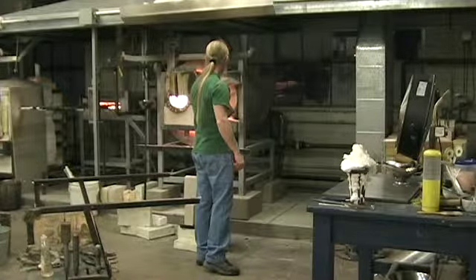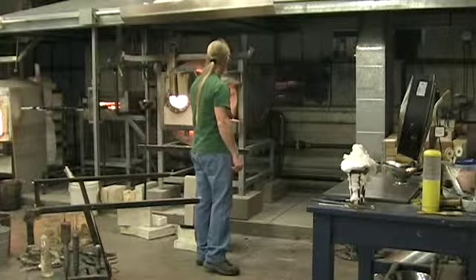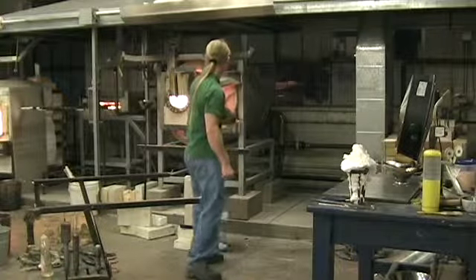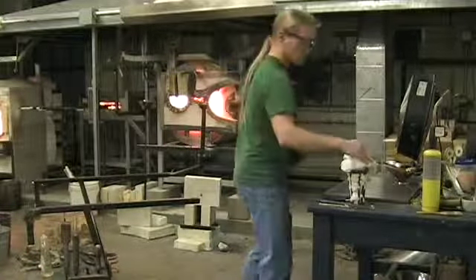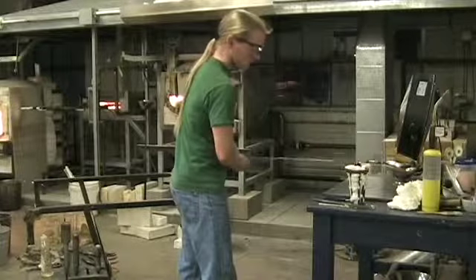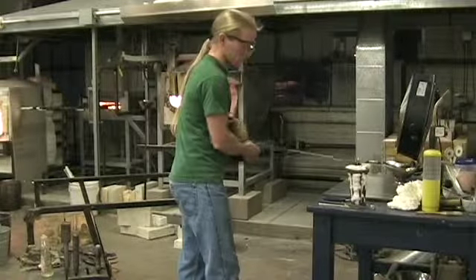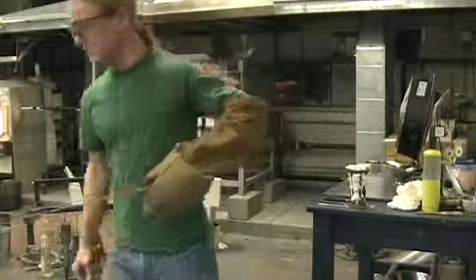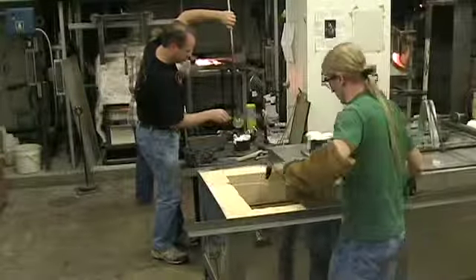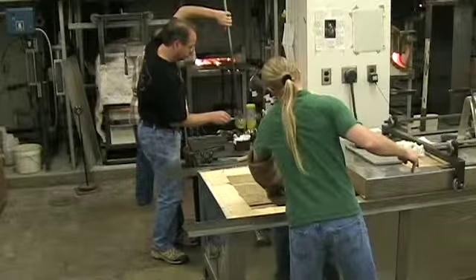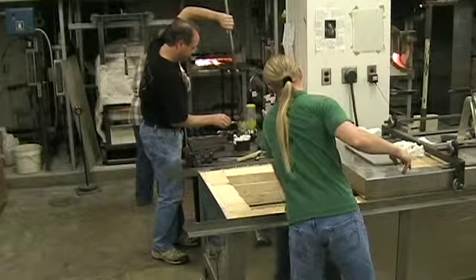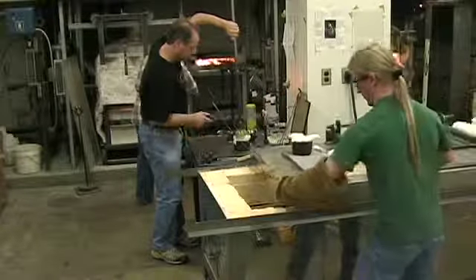Finally, I take the pepper to the annealer, which is like a big kiln that keeps the glass at 515 degrees Celsius. When we have filled the annealer with pieces, a computer controller lets it cool down gradually over 24 to 48 hours. Otherwise, if we left pieces out at room temperature for more than a few minutes, most would crack and shatter from the stress. So it is usually a couple days before we can hold the finished chili pepper.